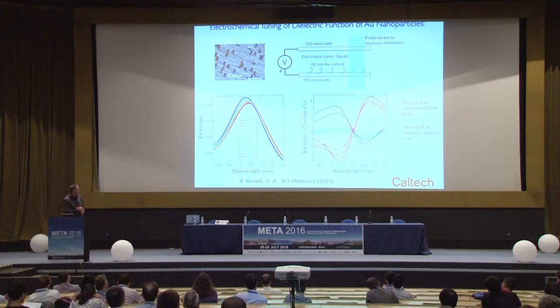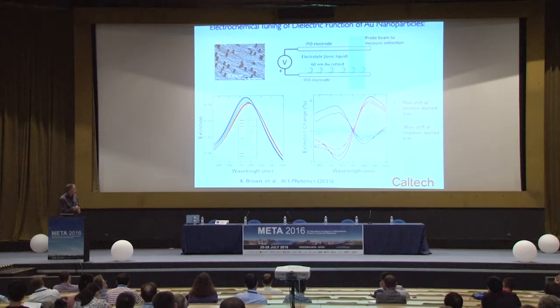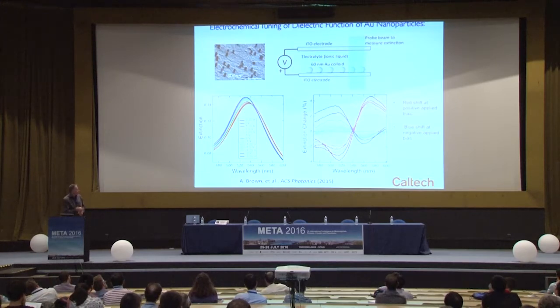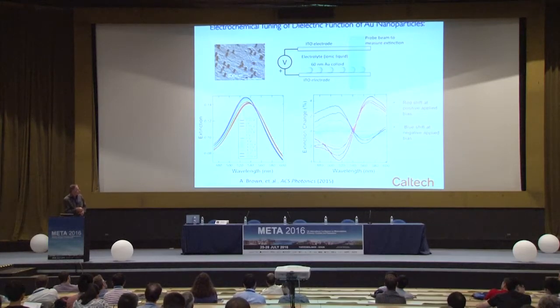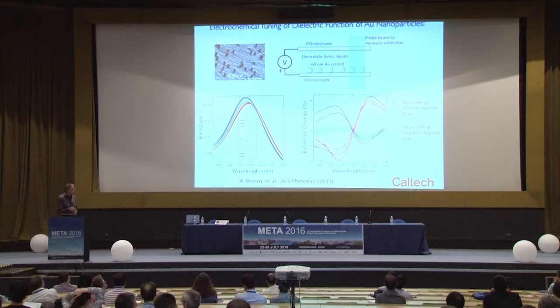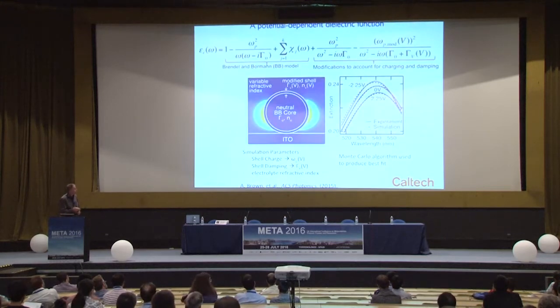And in so doing, we can see that with a few volts applied bias, tuned here from about plus 2 volts to minus 2 volts, we can actually see tunable extinction of the material and a change in the resonant frequency and also the line width. And so what we see, if we look carefully at this and we look at the change in extinction coefficient, is that we see a red shift for a positive applied bias and a blue shift in the extinction for a negative applied bias. And this is in accord with our simple Drude picture, something that occurs for a change in charge density of a few percent. So indeed, even metals are electrostatically tunable if we apply a large enough potential.